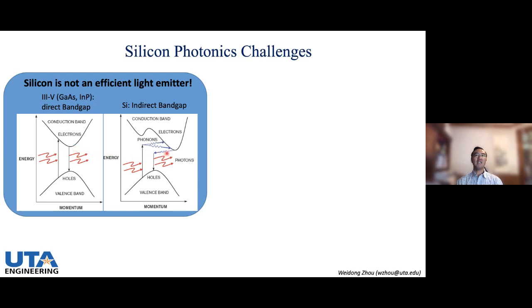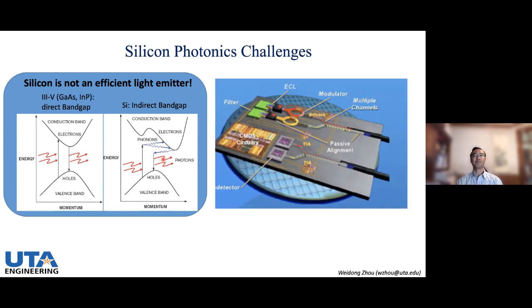On the other hand, silicon is an indirect band material because the minimum of the conduction band and the maximum of the valence band are not located at the same position in k-space. So it's inefficient for light emission. In fact, it's very hard to make a light emitter out of it.